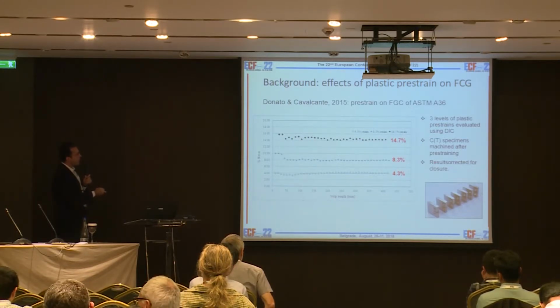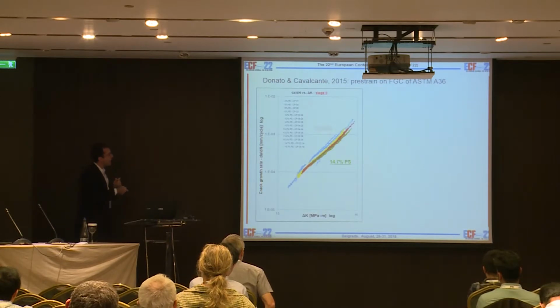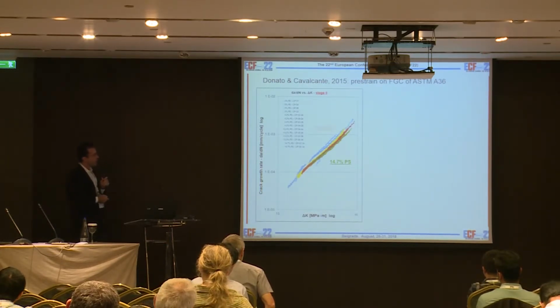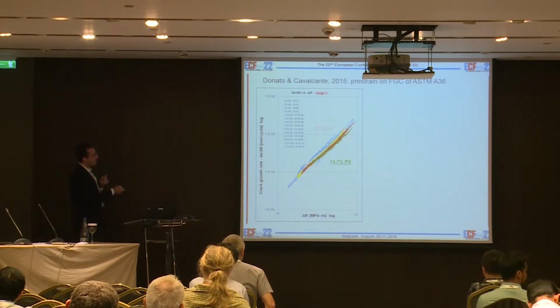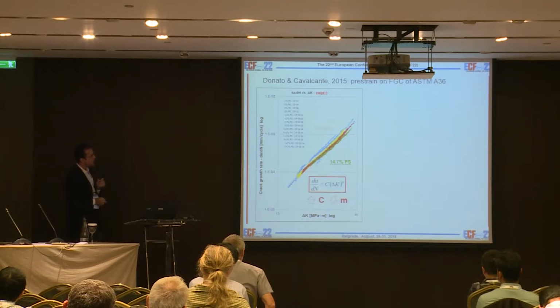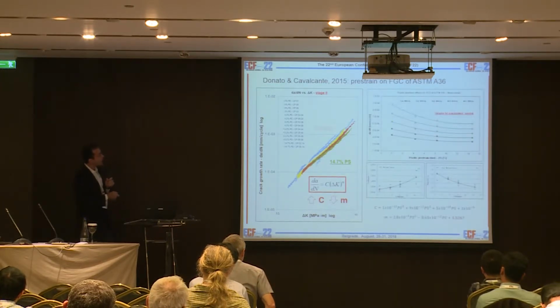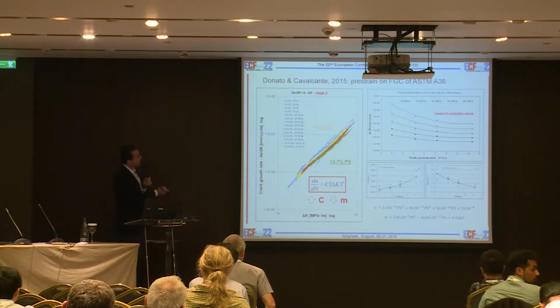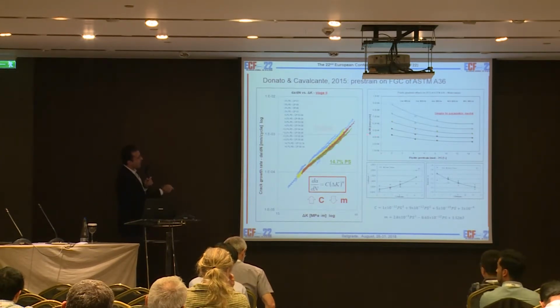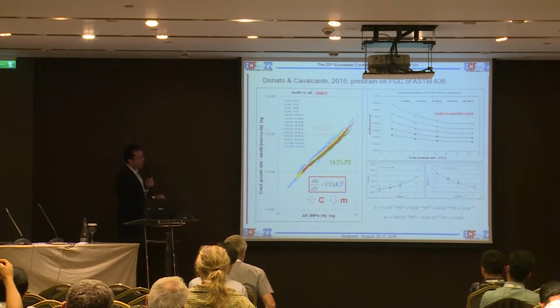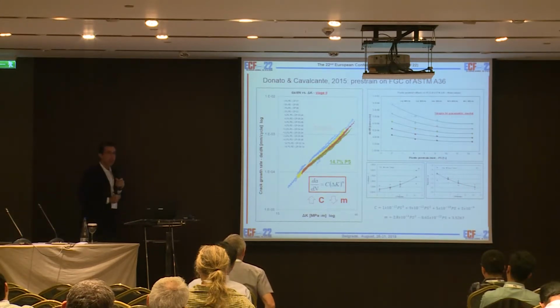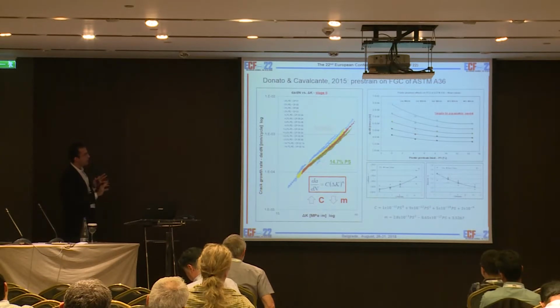So 3 levels, and the results were corrected for closure. Here you can see some of the da/dN versus delta K evolutions. The original is here, the 14.7% pre-strain is here, and using Paris law, we could characterize the effects of plastic pre-strain level on da/dN, and we could calibrate C and m values using a best fit for a model that is presented here. So one equation for C, one equation for m, and these are the best fits for all the conditions that I'm presenting here. The scatter is a little bit relevant, but I'm not discussing this point here.